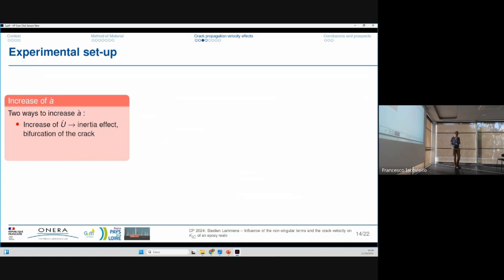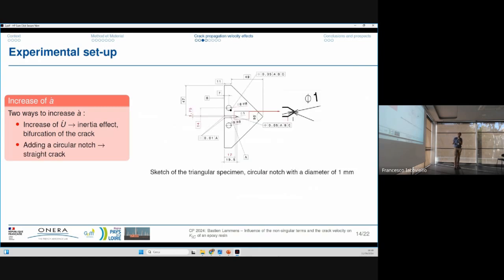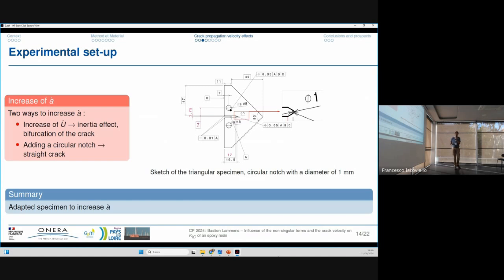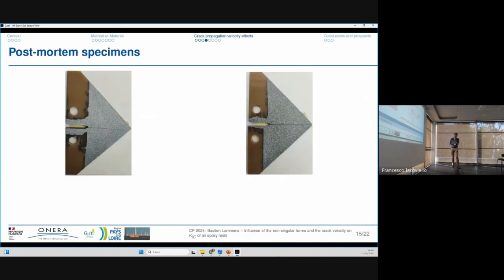We wanted to have crack propagation higher than this crack propagation speed, so we decided to change something. Because we could increase the loading rates, but we had inertial effects, and the crack path was not straight. We had a bifurcation of the cracks, so we decided to add a circular notch. We replace the sharp crack by a circular notch with a diameter of 1 millimeter to have an adapted specimen to increase the crack propagation speed.